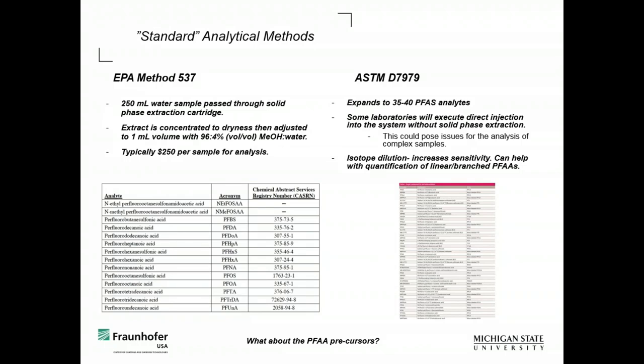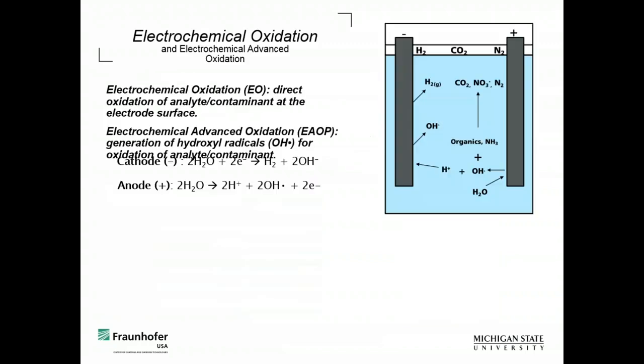I'll just highlight this. EPA method 537 gets you about 14 to 17. The modified method will get you 20 to 25, and then the ASTM method can get you 35 to 40. The trouble is, a lot of the ASTM methods use direct injection, so they don't really do a bona fide extraction procedure before they send the solution through to the mass spec. As I'll show, our processes require a degree of conductivity, and we are making ions as we treat, so direct injection is sort of a nightmare with our samples.